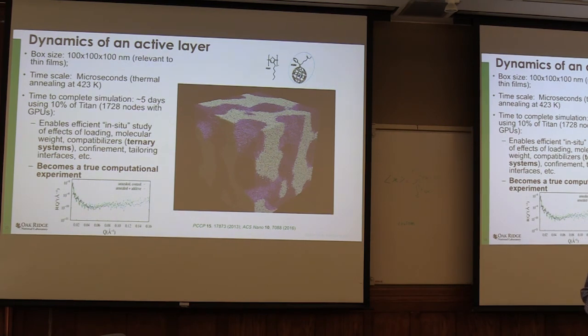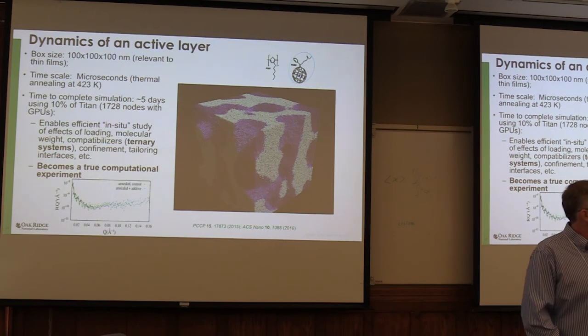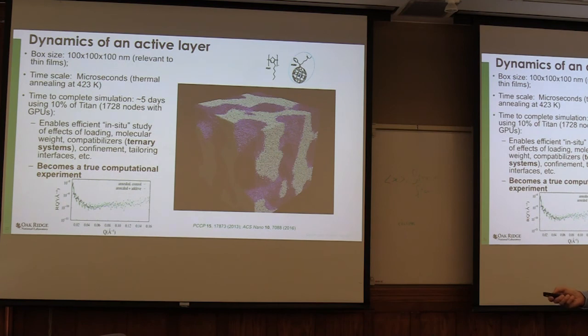So our question is, well, can we fix that? Can we just change the number of these guys to these guys, or the length of this guy, and optimize this morphology so that the domain sizes are shorter than the exciton path length, so that the thing will separate into electricity? And the answer is, yeah, you can. I won't show you all the details, but we were able to do that by changing the molecular length of the polymer. And we were able to compute out of that a scattering function and compare it directly to experiments to confirm that it's not all nonsense, right? So this was experimentally validated by doing neutron scattering.